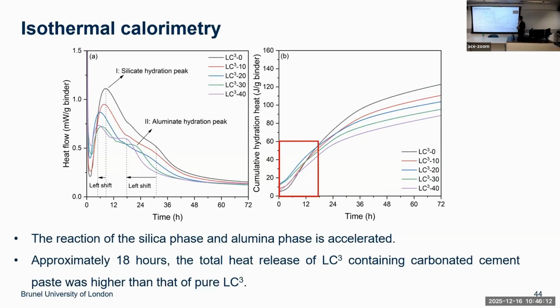We also measure the hydration heat, with the heat flow and the accumulated heat. You can see that we have two phases, the silicon phase and the aluminum phase. The silicon phase hydrates earlier than the aluminum phase. Compared with the red line, which is without carbonation, with carbonation the silicon phase hydration shifts earlier; it starts earlier. The aluminum phase hydration also shifts earlier, to the left. So the reactions of both the silicon phase and the aluminum phase are accelerated. Why do we need to accelerate it? Because LC3 generally, compared with Portland cement, has a lower early strength. That's the weakness of LC3.